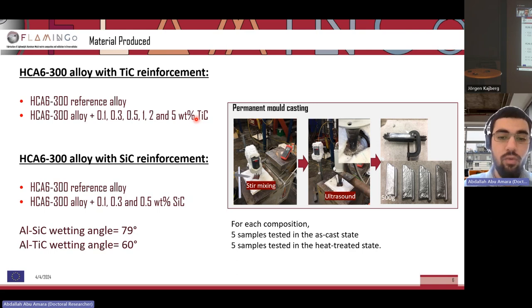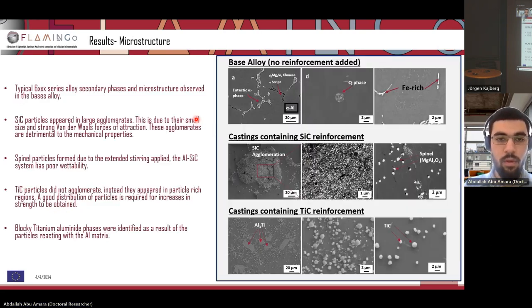And for each composition, we tested 5 samples in the as-cast state and 5 samples in the heat-treated state after heat treatment. So now we can take a quick look at some of the results.